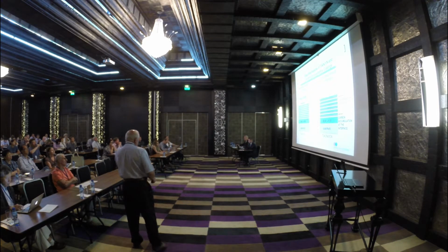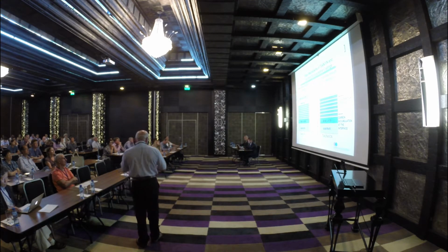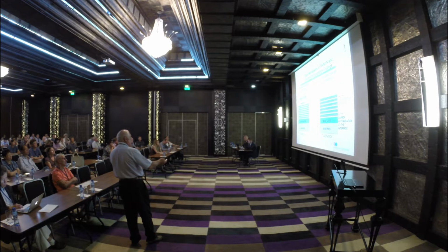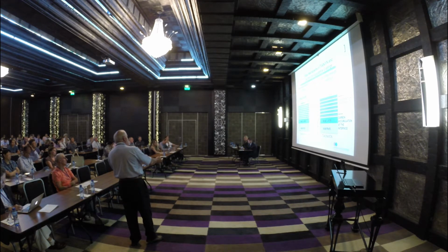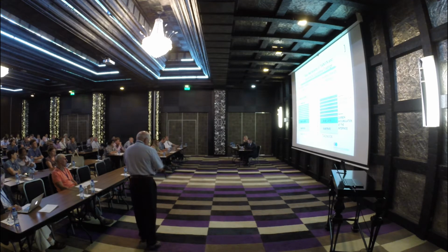Now, the main reason for this good performance is the accumulation of the carbon at the interfaces of the individual layers. I said that these individual layers are nitrides, titanium nitride or vanadium nitride. When you don't have carbon, the bonding between these layers is extremely strong, so you have a build-up edge formation, and when this build-up is removed due to the cutting forces, a big chunk of your coating will disappear, and therefore the lifetime is very short. But if you segregate carbon as we have done, then you have a very low shear strength interface. So when the build-up edge starts forming, the tangential forces will delaminate this interface, and you expose permanently fresh surfaces of this coating, and therefore you get this very good performance.